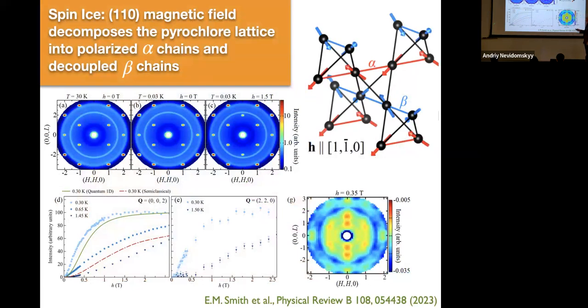So we can look at cerium zirconate in an applied magnetic field. There's a very interesting and easy to understand argument about any spin ice in a magnetic field along the 110 direction. This is a little piece of the pyrochlore lattice, and this red direction here is a 110 direction. You can think of the pyrochlore lattice as being made up of interpenetrating chains: those that point along a 110 direction, shown in red, and those perpendicular to that same 110 direction, shown in blue.